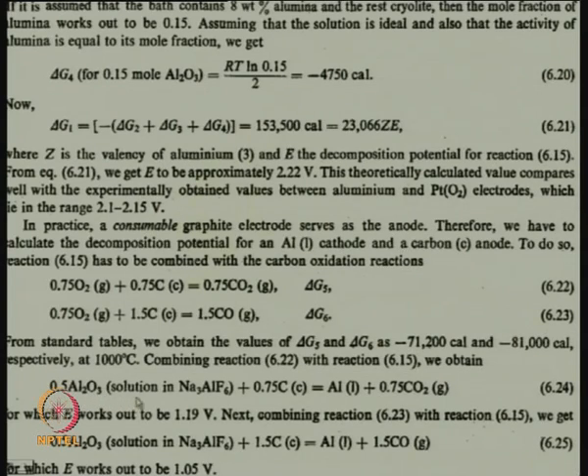Alumina in solution in cryolite reacting with carbon in the anode produces aluminum metal and CO2, or alumina in solution reacts with carbon in the anode and produces aluminum metal and CO. Whether it will be CO or CO2 will depend on temperature. You know, the higher the temperature, the more the CO; the lower the temperature, the more the CO2.